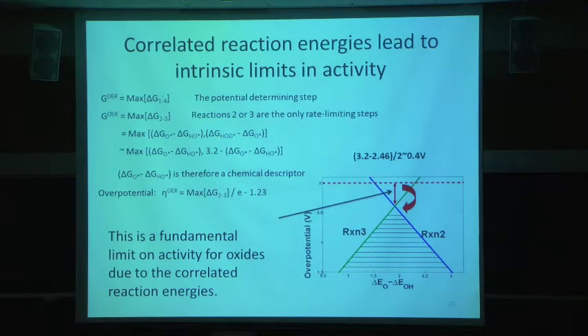Now another particularly interesting feature here is, as you go up this line here, there's a crossover point that makes you go back down in activity. And if you look at where the crossover point here is, it's at point four volts, 400 millivolts. It's actually quite far from the thermodynamic minimum.